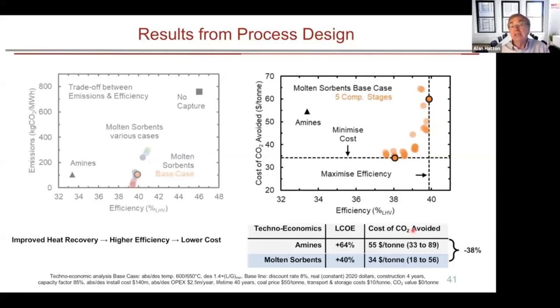Take the economic analysis. The levelized cost of electricity with amines goes up by about 64%. With the molten sorbents, we think it could be up to about 40%, significantly lower. And the cost of CO2 avoided would be shown here, $34 per ton relative to $55 per ton, around a 38% decrease in cost of CO2 avoided. Of course, there's a lot of work still to be done in this case, the materials of construction, stability, and things like that. But this rather extensive, exhaustive analysis here indicates there could be some strong advantages associated with using these molten salt absorbents.